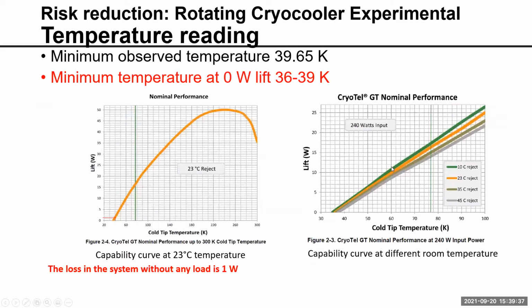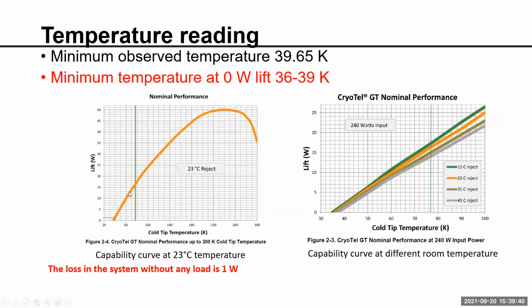So here we have some initial results. This is the performance of the cryocooler. At 0 watt, if we don't cool the sample, it can go down to 36 Kelvin. But if we keep it at 50 Kelvin, it can lift 5 watt of loss from the sample. So that's the target. While we are rotating the cryocooler at 3,500 RPM, which is the targeted speed, we should be able to keep the sample at less than 50 Kelvin. That's the experiment that we are trying to do at ECE.